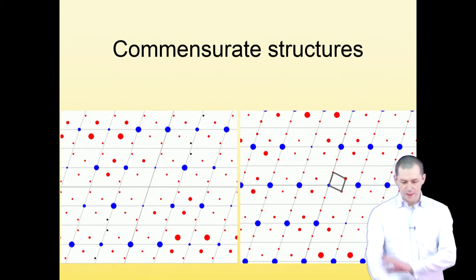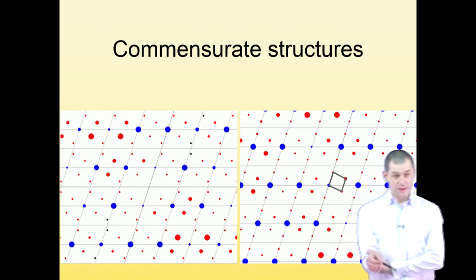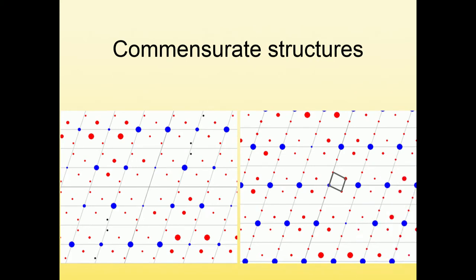I think I'll skip that. And this is an example, again, my favorite example, chromium diphosphate, not because there wouldn't be any other example in the world, but because I like it to show the concepts on one structure and relate them together. This is a scheme of the diffraction pattern of chromium diphosphate in its incommensurately modulated phase. And you see that this is a main reflection, this is a first order satellite, and this is a second order satellite, and it does not lie exactly on this line. It's close, but not quite.